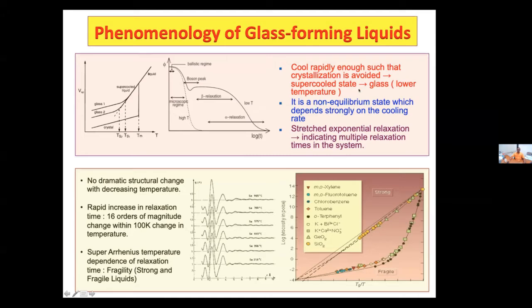So getting a glass is kind of an eventuality, and finding a crystal is a bigger problem, and sometimes it's an art. One of the biggest challenges in the glass problem is that as you cool or increase density, temperature and density being two parameters by which you can get the supercooled liquid leading to glasses, the relaxation time or the viscosity, which Srikanth already discussed, grows very rapidly. And depending on the nature of the growth, you have two broad classes of glasses, a strong liquid versus a fragile liquid.